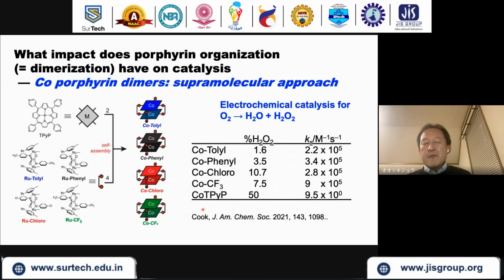So again, the dimerization has an effect, but the structure of the dimer is also important. Now, this is a more recent one published in 2021 by the group of Cook in the USA, and they produced a dimer using coordination interactions for these bridges and investigated the oxygen reduction reaction of these molecules, and they observed again a dramatic increase of selectivity as well as the catalysis performance.